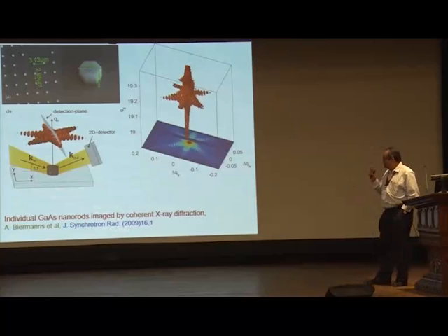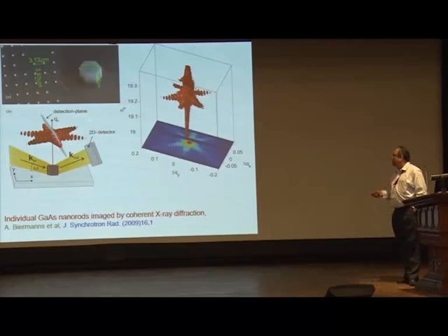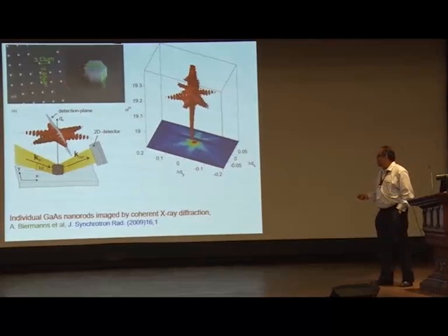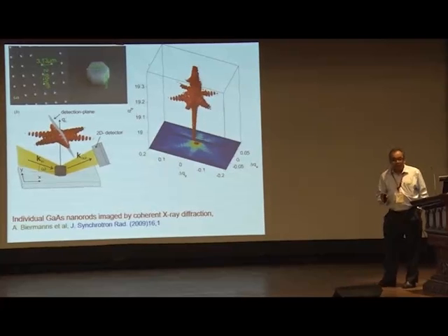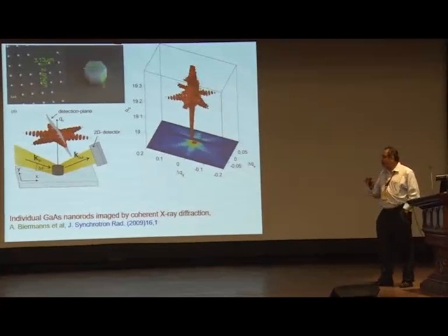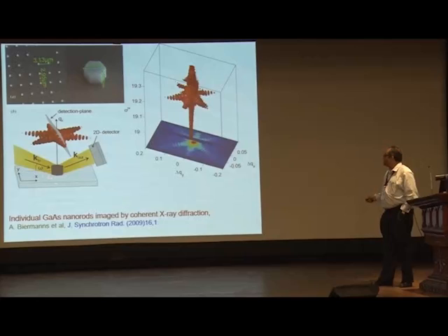The problem comes in a different way. As you can see, these are about 600 nanometer wide and about 20 nanometer high. That's good enough to absorb the X-ray. The problem comes when the quantum dot size gets less than 10 nanometer, or something like 20, 30, 50 nanometer.